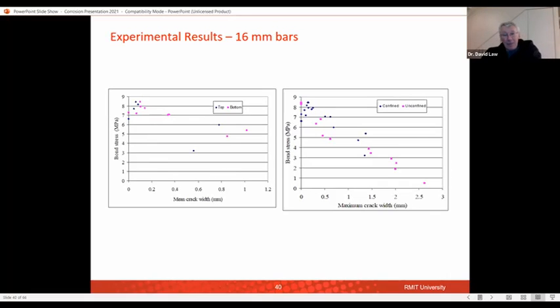So as you can see, there is a difference in top and bottom cast bars as well, and that's because the top cast bars perhaps have more space underneath them, so they could certainly increase a lot more in strength, because being top cast, there's probably a few more voids in those, and they get filled in by the corrosion product, and so you actually get a bigger enhancement of strength in those before you start to get the failure than you do the bottom bars, where you perhaps can see a little bit of an increase, but not too much before you start to get sort of the failure coming through.